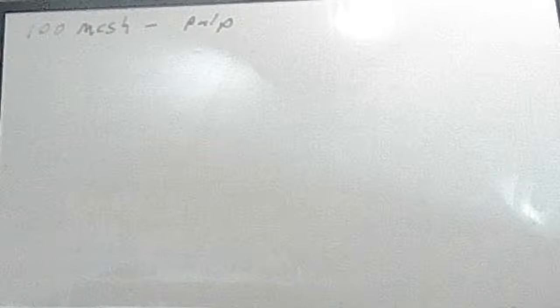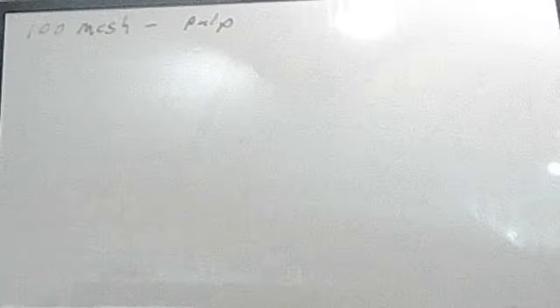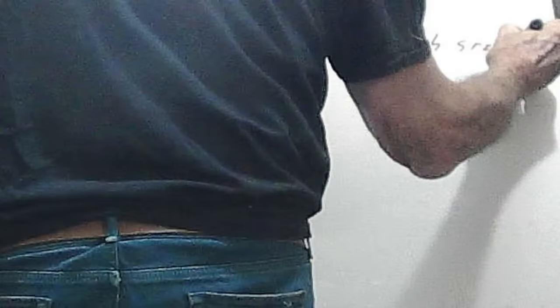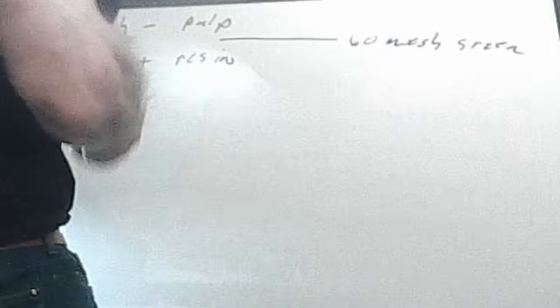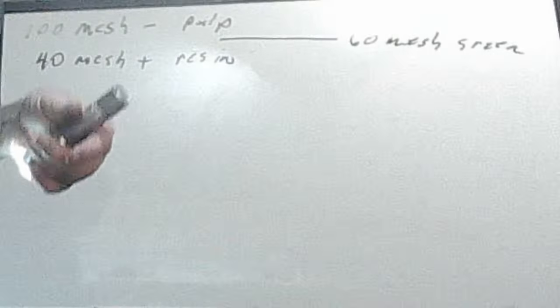So 0.015 inches is about 40 mesh. Okay. So if we have 100 mesh pulp that we're leaching, then 40 mesh plus resin, all we need is a 60 mesh screen. If we take these two and throw it on top of that screen, the resin comes off the top, the pulp goes through the screen, and wow, you got a really good separation.